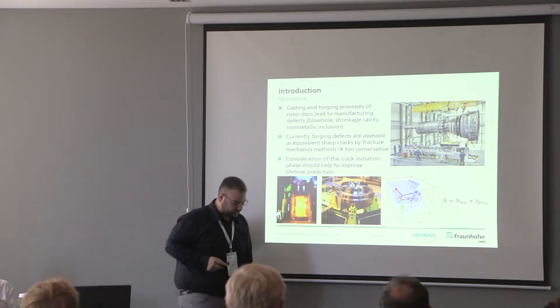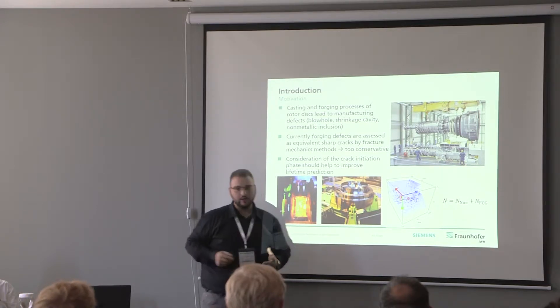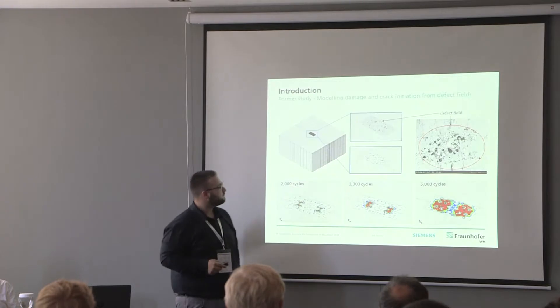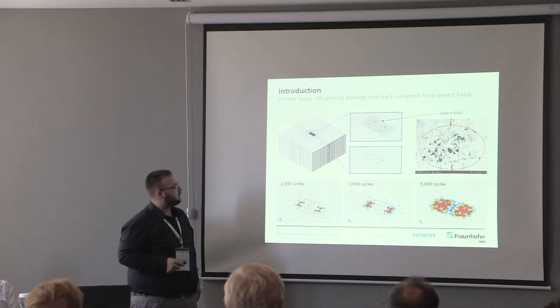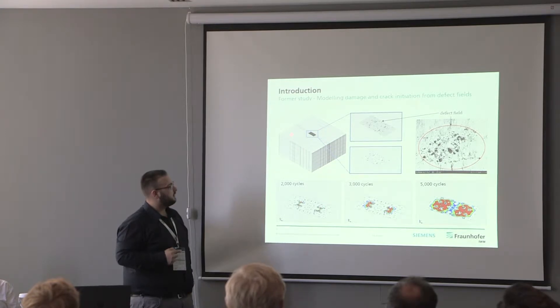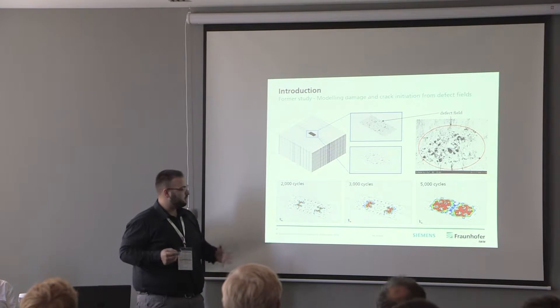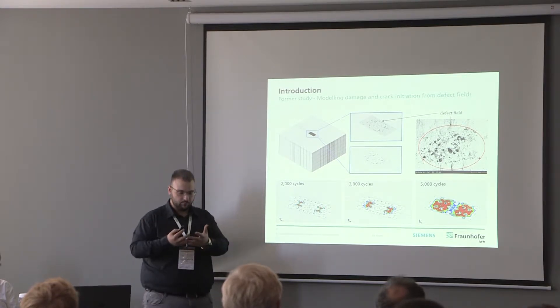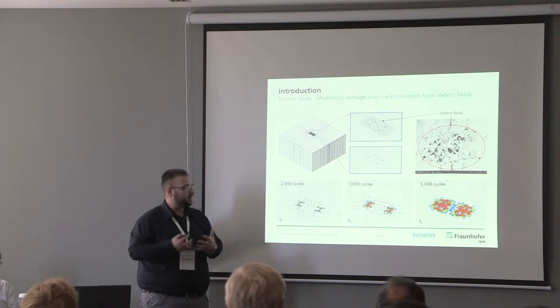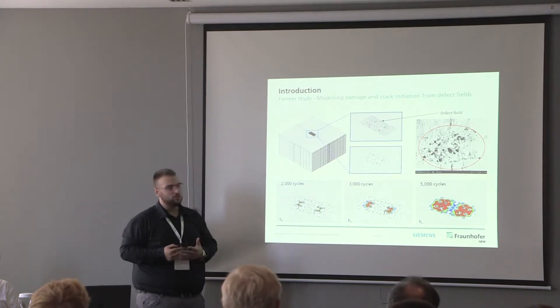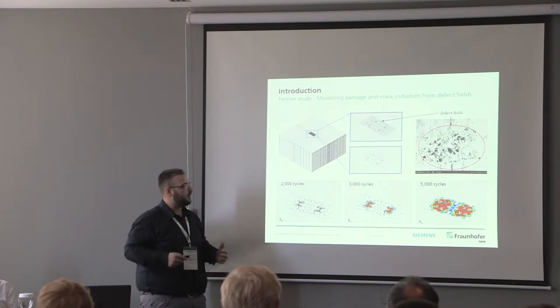We can notice that the lifetime is composed of the lifetime by the nucleation process and the lifetime by the classical fatigue crack growth. This is part of the former study. We see here a representative volume of a defect field. A modeling approach was developed to simulate the damage of the defect field and the nucleation, but the disadvantage was that the defect field was modeled in a very time-consuming way. My work was to automate this process.